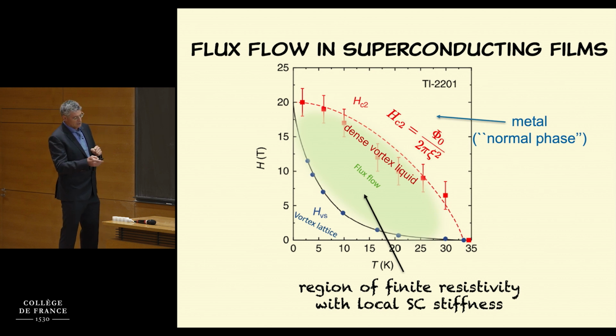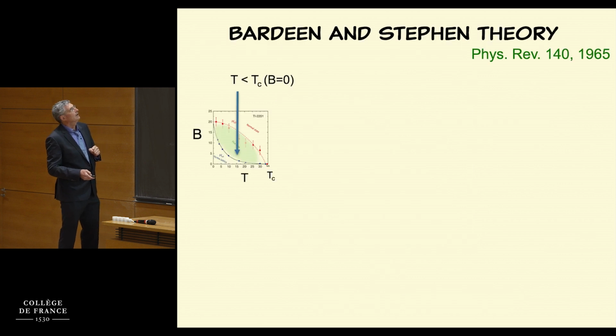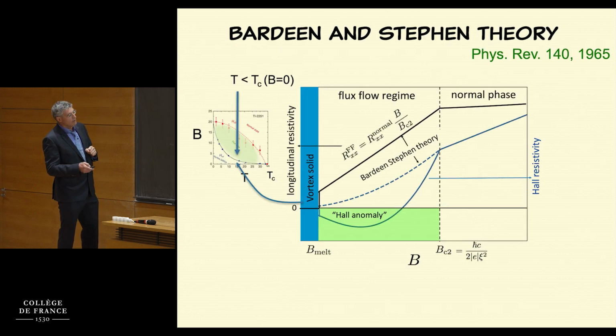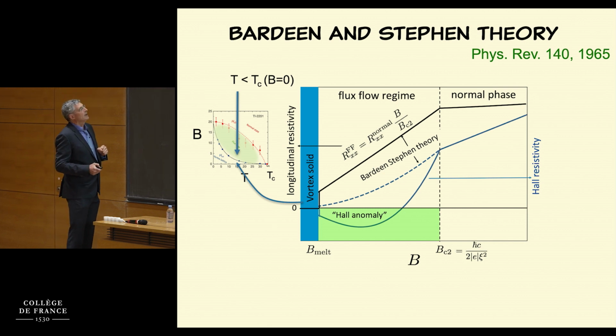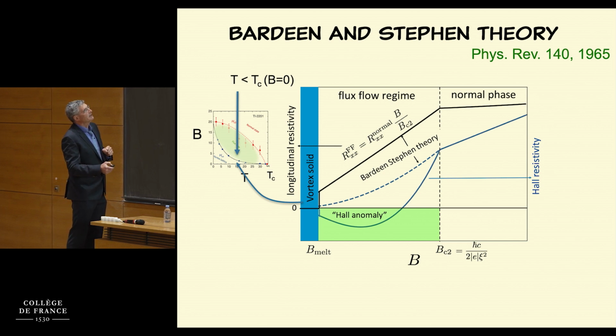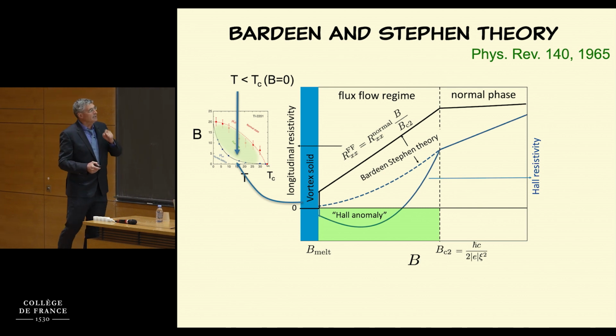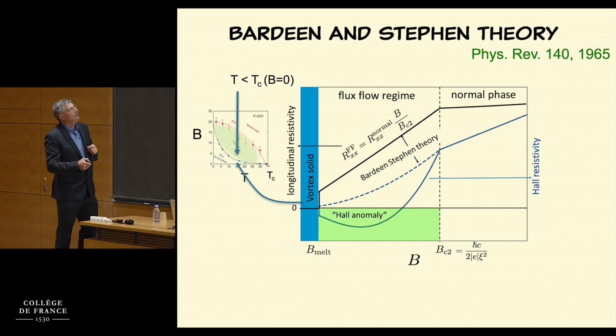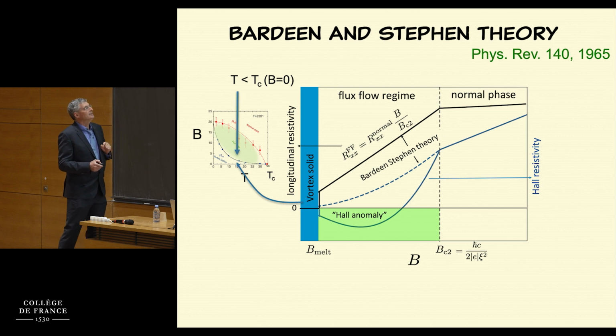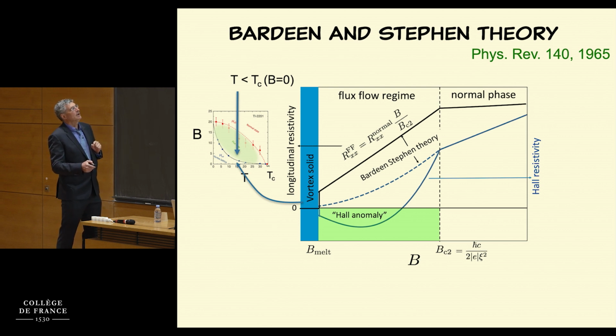Now, one wants to understand the transport in this regime, and Bardeen and Stephen did that many years ago. They wrote a theory that says that if you go perpendicular from high field to low field, you go from the normal state where you have some resistivity, and then at this BC2, nominally it will go down linearly with B with the magnitude dependent on the normal state resistivity. That's the longitudinal part. Now, with the same theory, they also stated that the Hall resistivity will have a B squared dependence and then cross over to B, and that is Bardeen-Stephen theory for the Hall resistivity. What is important in their theory is that the sign of the Hall coefficient in the flux flow and outside the flux flow is the same.